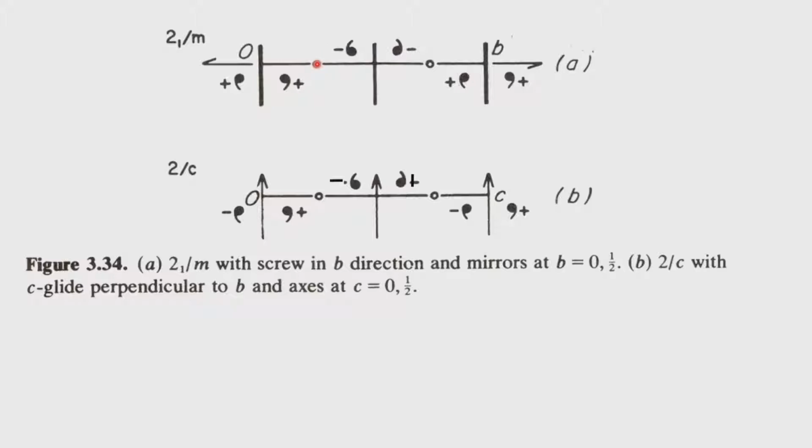If O is in this particular position, there is no other change. The 2-1 screw axis is going through this center of symmetry at 0 0 0, so the presence of the 2-1 screw is not altered. What is altered is the position of the mirror plane. The mirror plane now moves by 1/4. So if you have an operation which has a translation component, along with a component which has no translation, the no-translation component moves away by 1/4 from the origin.